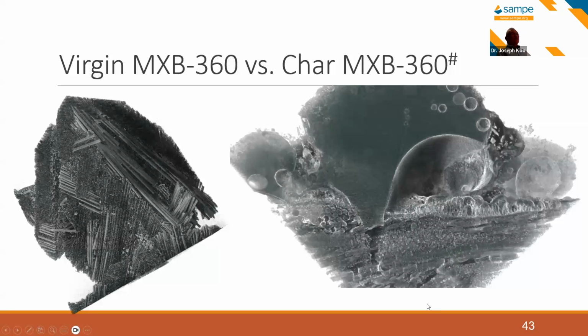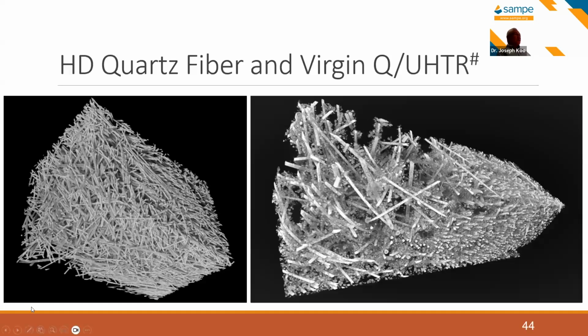You can see the big differences in the morphology of these materials. Okay, so this is something where we start to examine high density quartz fiber. What you see on the left hand side is a quartz fiber that we received from Singapore, and we were able to use micro CT in Berkeley to generate 3D structures.